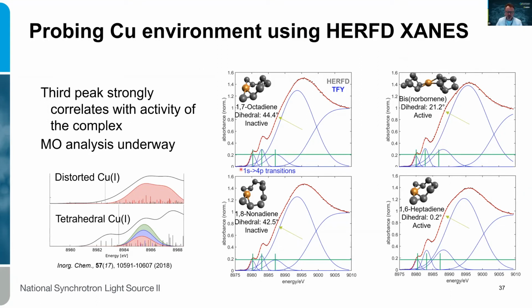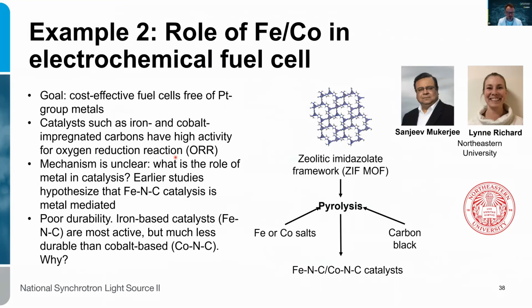So in this particular case, in this 1s-4p transition, we see that one of the components has a strong correlation with the activity. It's much more pronounced, and we are trying to do the molecular orbital analysis here on those samples.